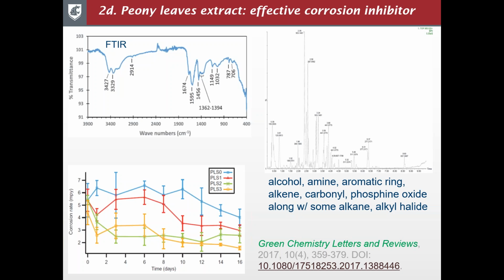The corrosion inhibition, of course, is around 70%, not 90 or 95%, but considering the low cost of this material, and it's also a waste utilization process. There's no liquid or solid waste produced from the process. It's a natural fermentation process, and we use some chemical tools such as FTIR, or Fourier transform infrared spectroscopy, to characterize what kind of chemical groups are in them, and used LCMS, liquid chromatography mass spectroscopy. Basically, we identify the effective components in them. Again, it's a mixture of things, mostly organic amines or phosphates.